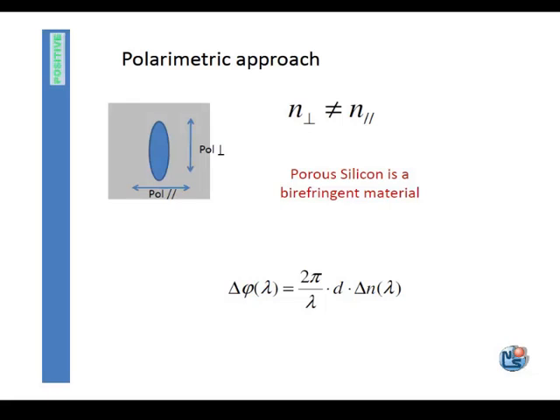That means that we have created a birefringent material, okay? And you can say, yeah, but you showed us that pores are nearly circular in porous silicon. That's true, but if you look at a circular pore under an oblique incidence angle, it becomes an ellipse. That means that porous silicon can also have a birefringent form, and we can detect variation due to the binding, for example, of specific proteins by looking at how this birefringence changes, and this birefringence change is translated into a dephasing